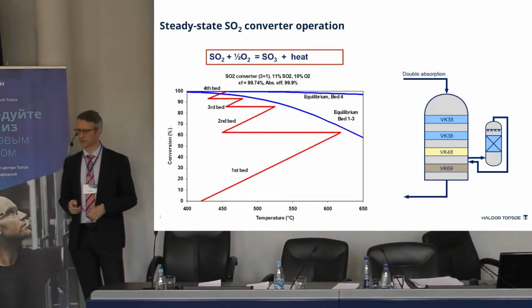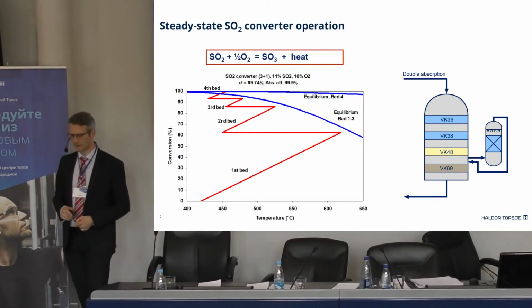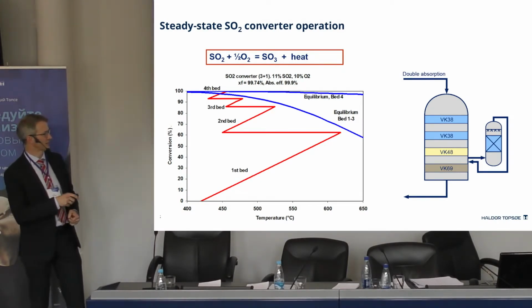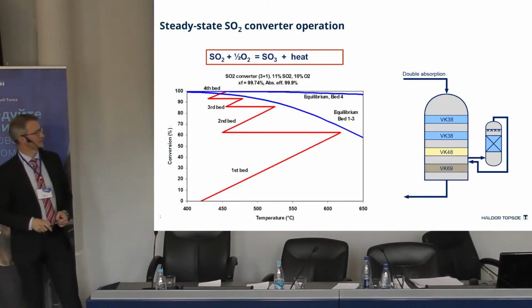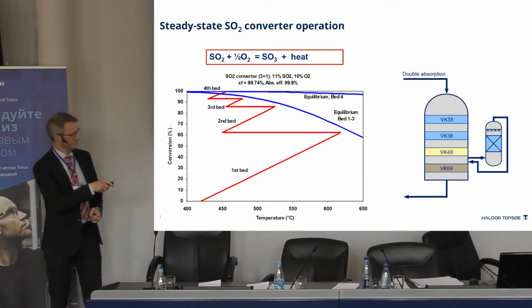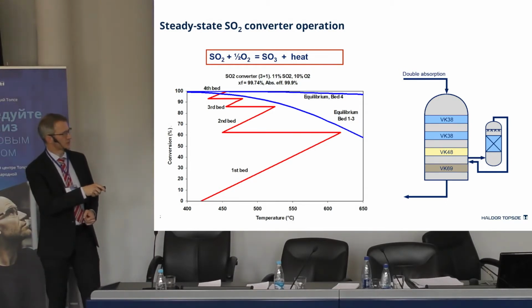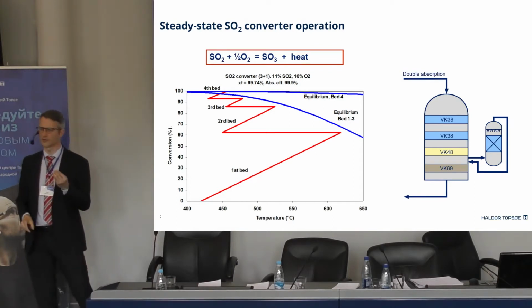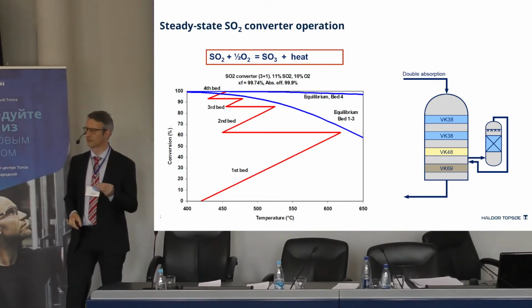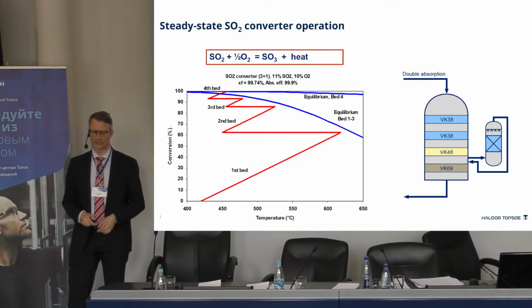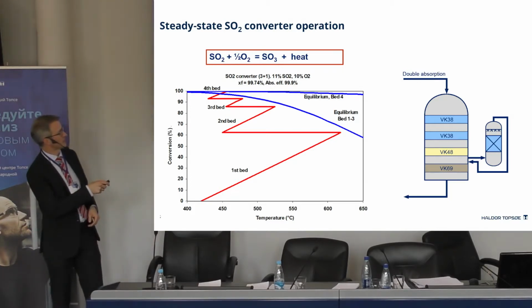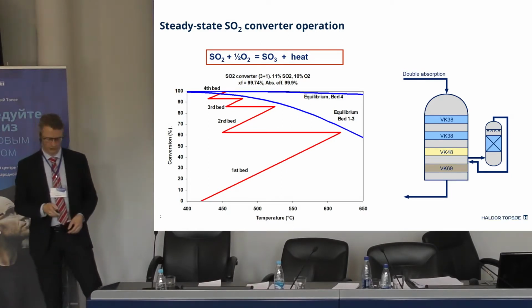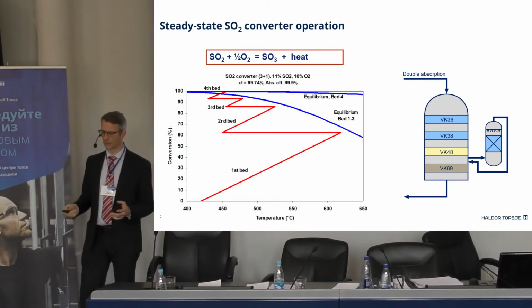This is a steady state operating curve for a sulfuric acid plant, a textbook example. You can say you have a temperature increase over each catalyst bed, and in this configuration, it's a 3+1 double absorption plant. After 3 beds, you remove some of the SO3 product, and then you can shift the equilibrium further to the right. In this way, you get this blue equilibrium curve for bed 4, and you can get to high conversion. And that's all very well, and we do that all the time.